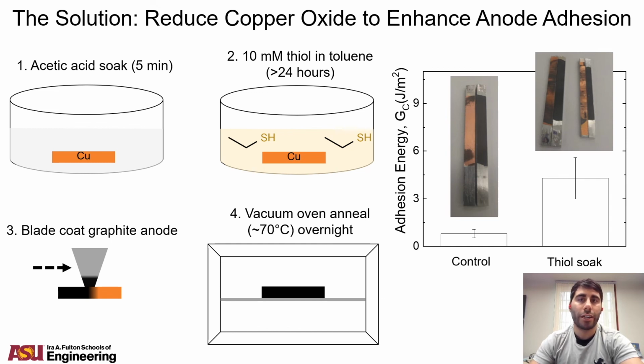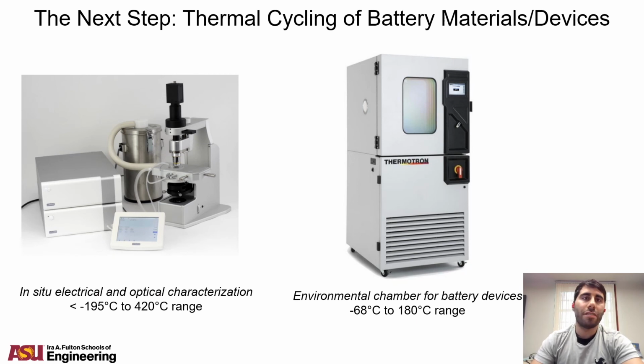In fact, you can look in the images on the right-hand side and see that there's actually some cohesive fracture within the graphite itself with the addition of this thiol. And now we're interested in seeing if this improved fracture energy can actually lead to longer cycle lives and reduction in the effect of the knee, particularly when undergoing thermal cycling instead of just electrochemical cycling.